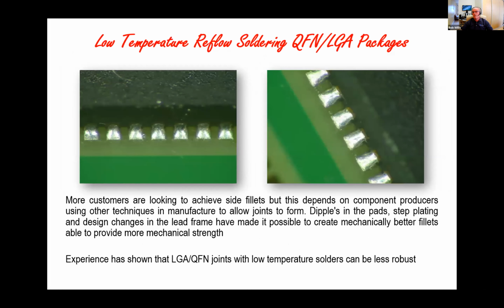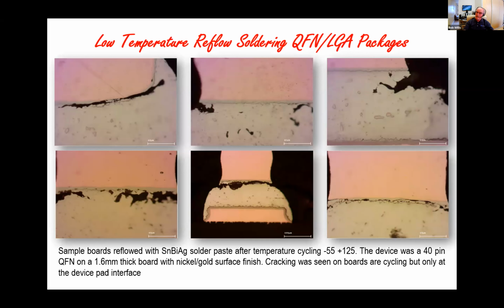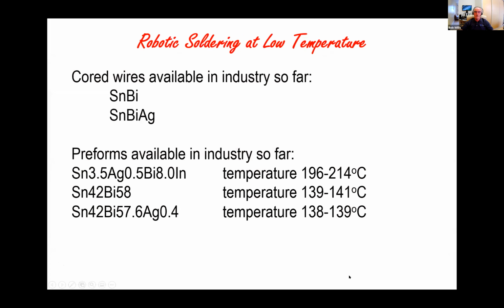We also did some work on QFN, LGA packages. And again, because the packages are changing, improvements to the design to improve reliability, that's good for the automotive industry. But for other types of industries, perhaps not as demanding as that, the low temperature materials may well be used. But we can see with temperature cycling that we can introduce failures. And these are examples of some failures that we saw in our QFN work. And you can see these microsections and the ruptures taking place between normally the termination and the bulk of the solder rather than anywhere else in the structure. But that's just some nice examples.